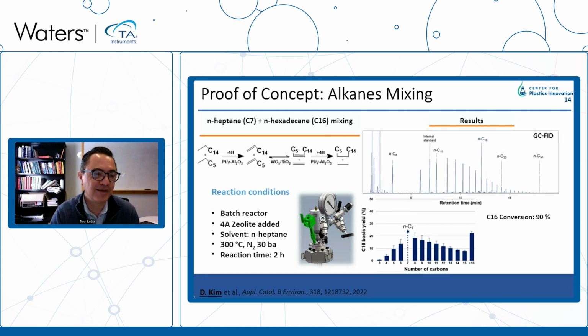All right, now we're going to add the two components. I'm going to start with alkanes, the platinum catalyst, and the tungsten catalyst. We're going to start not with a polyethylene just yet, just a model, for which we're going to use hexadecane. We're going to mix it with heptane in the presence of platinum. The platinum will remove hydrogen and form olefins. The tungsten will mix these pieces to make a mixture of olefins of different molecular weight. And then the platinum again is going to add the hydrogen.